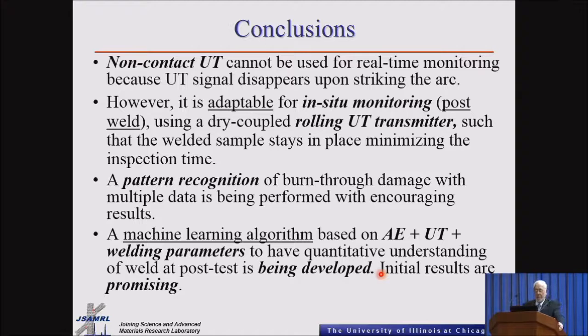This leads me to the conclusion, and I'm sorry, I went a little over time. First of all, we can see that non-contact UT cannot be used for real-time monitoring because the UT signal got pretty much blocked by the arc, by the magnetic field created by the arc. However, it is adaptable for in-situ monitoring, post-weld, using a dry couple rolling transmitter. A pattern recognition of burn-through damage with multiple data is being performed with encouraging results. A machine learning algorithm based on the acoustic emission, UT, and welding parameters, to have a quantitative understanding of the weld at post-weld test, is being developed.